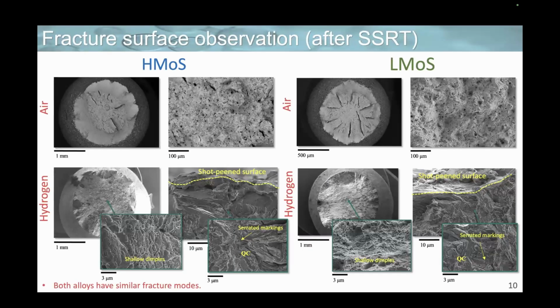Also, after SSRT tests, we performed the fracture surface observation. So for both steels, for the test conducted in air, we have a typical ductile fracture. What changes to the brittle fracture once the specimens are exposed to the hydrogen environment? Regarding the fracture surface of the specimens exposed to the hydrogen environment, the central zone remained of ductile nature, so we have shallow and dense dimples, while on the edges of the fracture surface, we can see the characteristics of a brittle and quasi-cleavage fracture with present serrated markings. However, we can say that both alloys in general have similar fracture modes.